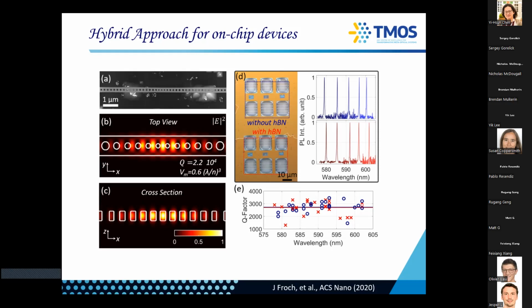And this is nice because then your mode leakage from the cavity would leak further and will interact stronger with the emitter. So we are still in the coupling mode. It's still an evanescent coupling where the mode is leaking. That is what is coupled to the emitters, but you have more leakage than if you would have designed a purely silicon nitride cavity and then put something thick on top. Okay. So does it work?